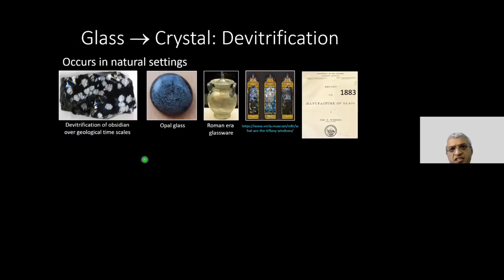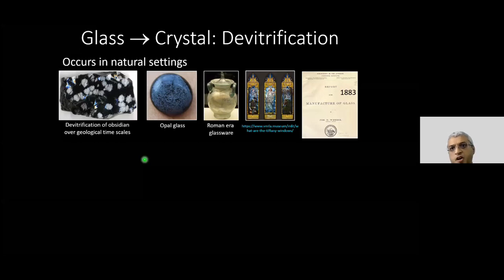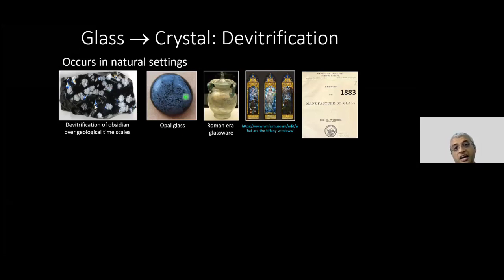So what I was telling you is that the glass is metastable, which means there is always a drive to form a crystal. And this is something that occurs in a natural setting. For example, this is obsidian, which is volcanic rock. And those white patches that you see are crystals that are formed over geological timescales. This is opal glass, which is once again devitrified. So the white spots again are crystallites. Roman era glassware. So these are things that people have unearthed and have found that actually the kind of spots that you see in them are basically crystalline. And just to point out that people were worrying about devitrification. So this is a book that's publicly available. So one can actually see that devitrification was something that people worried about even before they knew atoms existed. Okay.